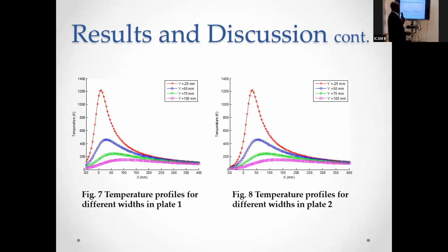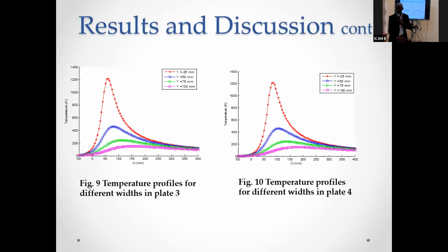Okay, next slide. Here we look at the temperature profile at different widths of the plate, at Y equals 25, 50, 75, and 100. Here is plate 1, plate 2, and then plate 3. Since we said we have perfect thermal contact between the plates, the results are almost the same, because that was the first thing we considered. Perfect thermal contact. This is for plate 1. Again, this is for plate 3 and then plate 4.